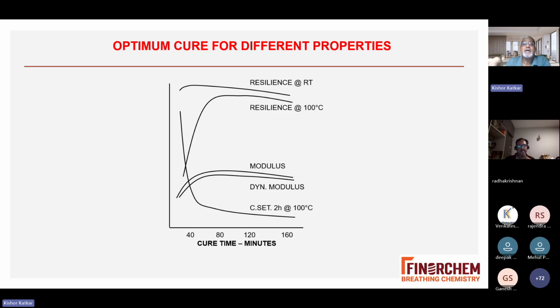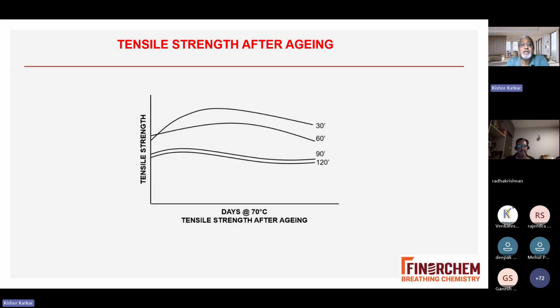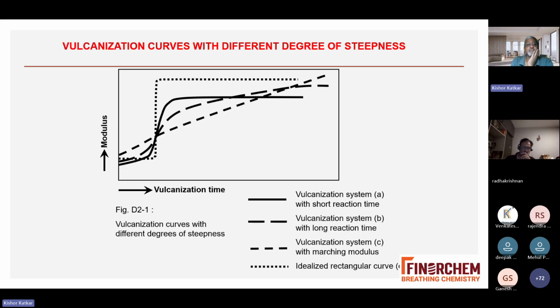Obviously, you have to add minutes of cure time depending upon the thickness of the part. That is additional. Okay. Here you can see I have mentioned that even aging property is important. In this case, tensile is cured at different timings: 30 minutes, 60 minutes, 90 minutes, and 120. What do you observe? 30 minutes gives the higher tensile, also in the original, and 120 gives the lower. When you age this product, you will find there is a drop in the tensile strength. The higher the cure temperature and the longer the cure time, the bigger the drop in tensile. So these are also important.